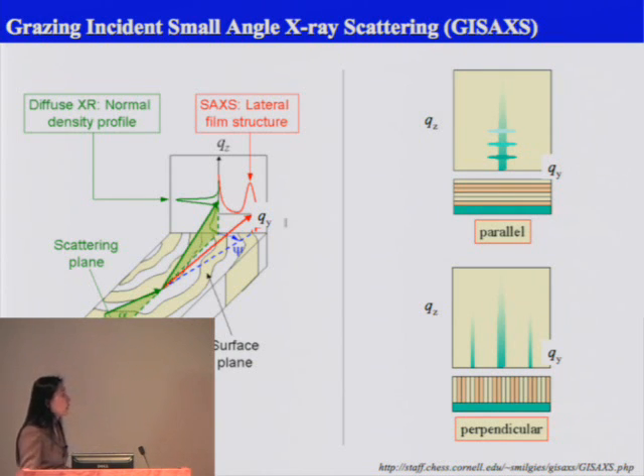So in order to make sure, you do AFM at a micron scale, maybe sometimes 2 micron, maybe even 10 micron scale. But it's really hard to convince people that I'm having the whole substrate have all the cylinders aligned in one direction, all the grains growing in one direction. So for that, we do grazing incidence small angle X-ray scattering.